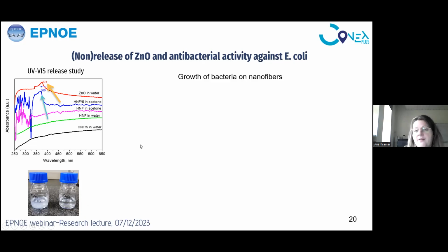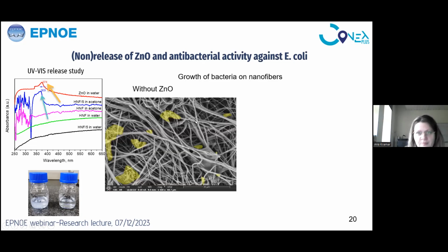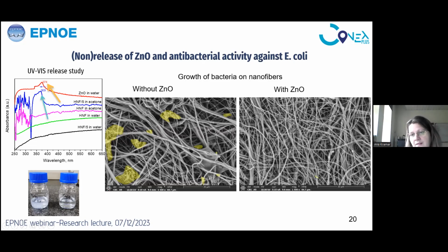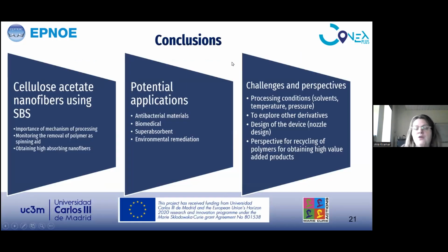We also studied the antibacterial activity against E. coli, and we analyzed the growth of bacteria on our nanofibers. Without zinc oxide, here you can see with the yellow areas in the scanning electron microscope image, we can see bacterial colonies that are preserved on our nanofibers. But when we add zinc oxide, we almost have no colonies. We found one small bacterium, and we were looking and looking and looking during the measurements, but we found only one small lonely bacterium here, while other parts of our non-woven material were completely clear from bacterial colonies. So to conclude,